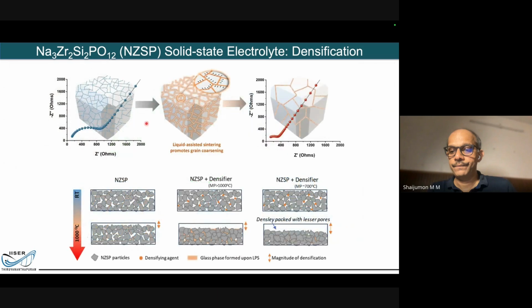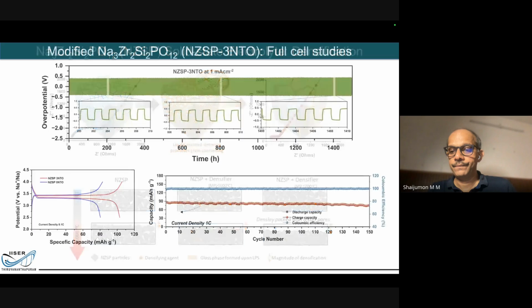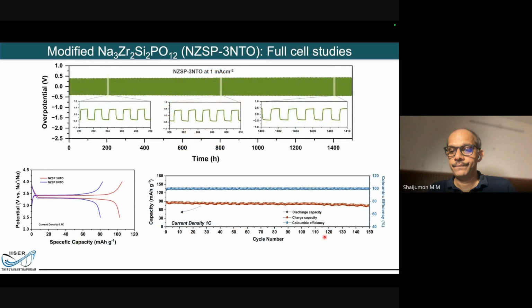So this is schematically shown here, because I can take the impedance initially, and some sort of sintering happens, and finally this is what happens. These kind of materials which are added go and align at the grain boundary, and basically bring down my impedance. And this densely packed material will have fewer pores compared to the parent or pristine material, right? And how do I test it? Well, don't worry about it, because I'm just taking you through some results now. There are multiple ways of testing how good this whole process is. Basically, there is something called symmetric cycling, we call it.